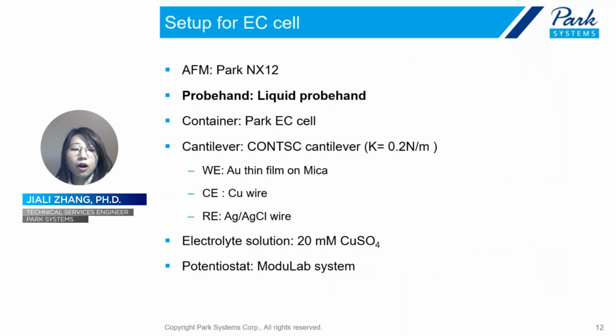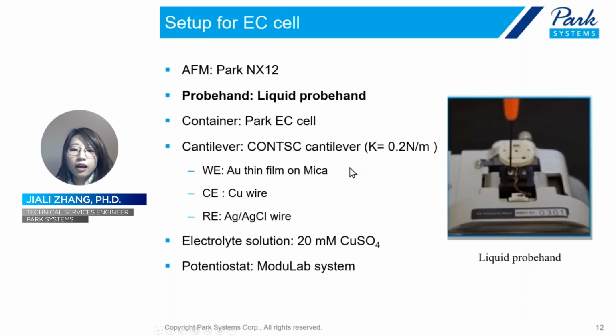So this is our experiment conditions for today's copper deposition and dissolution using EC-AFM. In the experiments, we use a liquid probe head for AFM imaging in liquid. It is made of PEEK material, therefore it is resistant to most buffer solutions, including acid and base. The solution we use will be copper sulfate to provide copper ions, and the working electrode will be gold thin film on mica. And this is a counter electrode and a reference electrode.